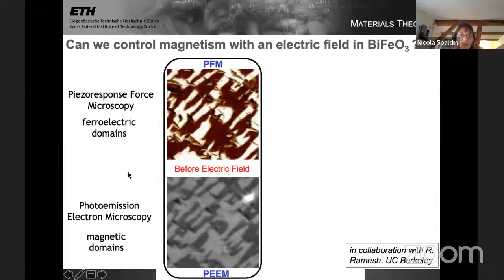In the interest of full disclosure, I have to be completely honest here and admit that bismuth ferrite is actually an anti-ferromagnet. So what's being imaged here are the anti-ferromagnetic domains. So it has these very large local moments on the ion, but they anti-align. So it's not ideal in terms of what we would like for a multiferroic. But these are the anti-ferromagnetic domains. Clearly we have this coupling, right? We have a coupling, or correlation, between the electric dipoles and the magnetic dipoles.